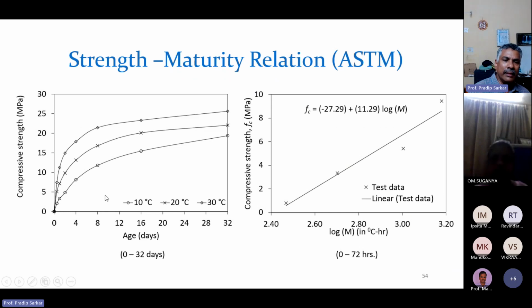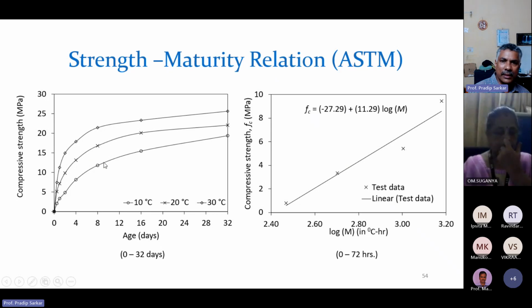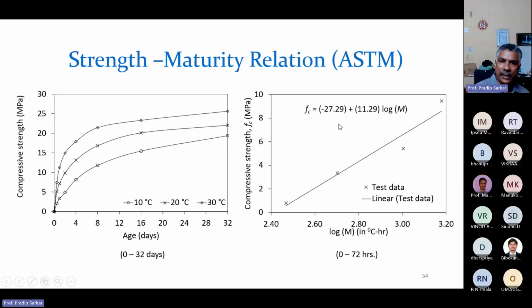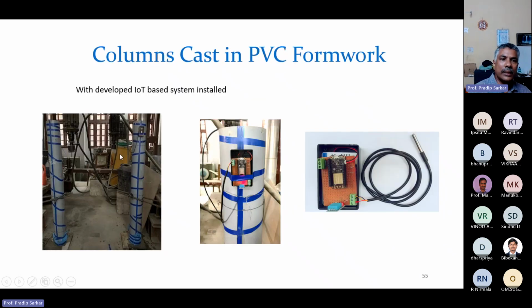So in the strength maturity index, this is developed in the laboratory, and I have already shown you that information, that the strength maturity relationship is developed. These A and B values are developed, and datum temperatures are also developed. And we have done some laboratory tests where the columns are cast with the vertical form, and in all the columns we put the LoRa end node here, and we are getting the data from the LoRa end node, and the LoRa end node tells us when to remove the formwork.